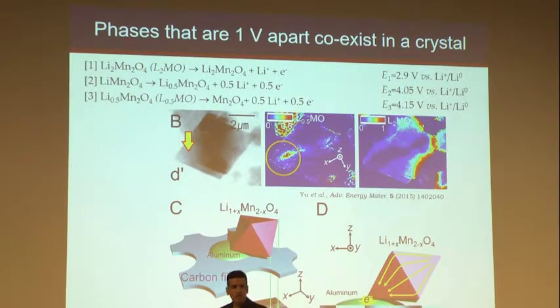And so the image that I'm showing in this slide is just one snapshot at one potential in the cell. So that's the image on the left. The images on the right are concentration plots. So this is basically taking one of the phases that we found in the sample by doing linear combination fit and plotting the concentration in the particle. And so this plot in the middle is this Li 0.5 phase, and the plot on the right is the Li 2, which is all manganese 3. And so you can see that in the same particle, both phases are present.